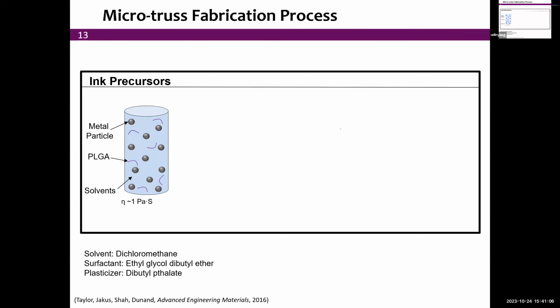So here's in principle how it works. We are creating a suspension with the metal particles or the oxide particles. We have a binder, which is a polymer, and the solvent. The solvent is dichloromethane, which evaporates very quickly. As I said, we add surfactant and plasticizer if we want to have really flexible structures that we can bend and do origami, as I'll show you in a second.